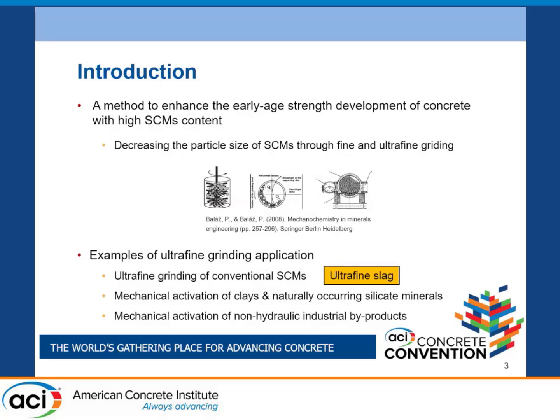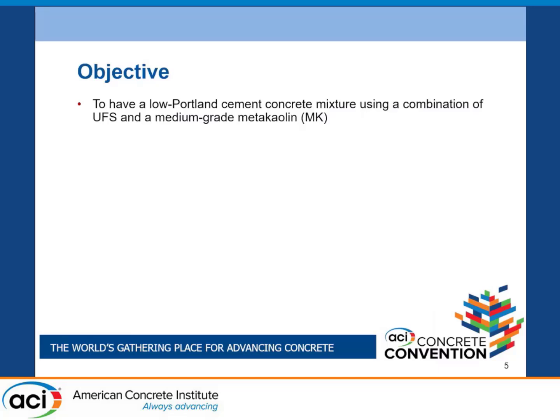In this study, our focus is on ultra-fine granulated blast furnace slag, or UFS. The objective of my study is to have a low Portland cement concrete using a combination of UFS and a medium grade locally available Metakaolin. In this regard, first we prepared and characterized our UFS, and the UFS that we were aiming to achieve had a D50 smaller than 1 micrometer.